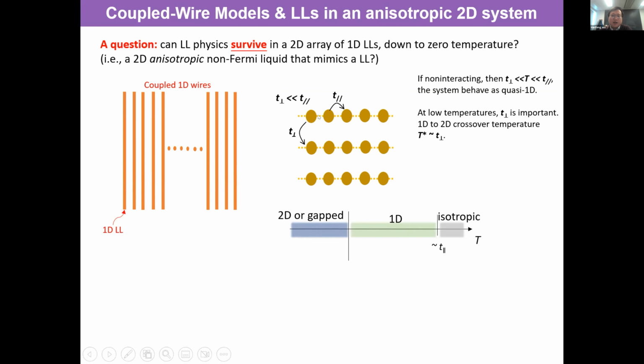You can look at this system more carefully using the picture that I'm showing here. Now you can replace the wire with a lattice, a crystalline lattice. The electron can hop between sites along the wire, so the hopping is t parallel, which is big compared to the interwire hopping t perpendicular. In the anisotropic case, which mimics this coupled wire model, t perpendicular is much less than t parallel. Then you can ask, do you have Luttinger liquid physics? And you do, when the temperature is in between t perpendicular and t parallel, because if the temperature is high compared to t perpendicular, essentially t perpendicular is not important.